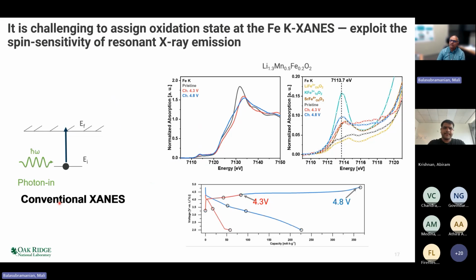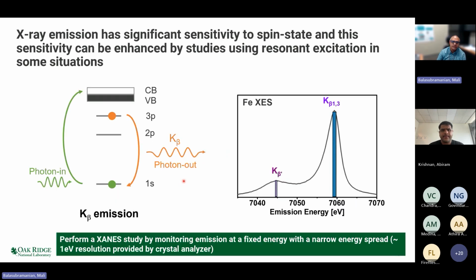So if you look at the conventional XANES of iron, you will see that as you charge the material to 4.3 volts and 4.8 volts, there are small changes in the pre-edge, but it turns out that the pre-edges of all these different samples, iron in a 4-valent state, iron in a tetrahedral site, and so on, unfortunately overlap. Furthermore, the iron 4 oxygen bond distance and the iron 3, when the iron occupies a tetrahedral site, and the oxygen bond distance tend to be very close. So assigning oxidation state simply based on X-ray absorption or based on measuring iron oxygen bond distances is a little bit more complicated. So to understand this, we resorted to trying to use spin sensitive X-ray emission.